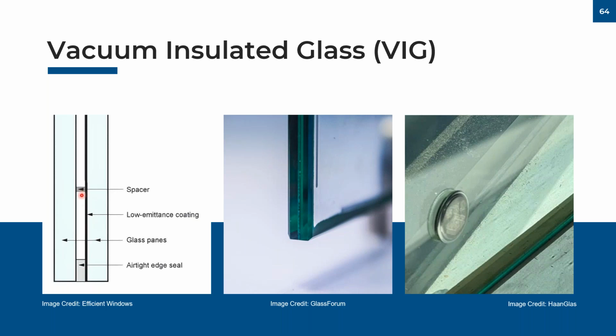They also employ a spacer, or these pillars, all throughout the assembly to keep the two sheets of tempered glass from caving in on each other. And so you can see the edge of this, the profile of it is very, very thin, starting at just over 8 millimeters thick, front to back. So very, very thin system here. It's a great solution to replace existing single pane systems on the market. And what you'll see, because this is a vacuum, is a port where all that air is evacuated out of it and then plugged at the port. So each of these vacuum insulated glass units would have this port at the perimeter somewhere.